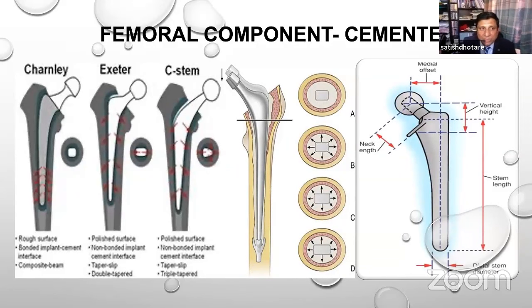Now, when you are choosing the femoral components for the cemented stem, you need to understand the principle and which are the good cemented implants, time tested with longevity, which are currently Exeter and C-stem. We are currently using the AMT stem, which is a modification of the C-stem. But the old Charnley stem had a composite beam design, with a relatively rough surface, although it was tapered, with good cement bone integration, but it caused increased stresses on the cement, leading to cement mantle breakage or fractures and early failure as well.